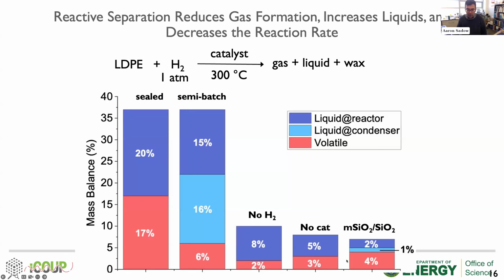So this also gives us some opportunity to do some controls. Without hydrogen, without catalyst, you see that the conversion basically doesn't happen, and nothing ends up being transferred to the condenser. And only if you have a little bit of silica do you get anything, and these end up being kind of broad hydrocracking kinds of products. So that strongly indicates that there's a synergy between the catalyst and this reactive separation for increasing the reaction and the selectivity of the conversion.